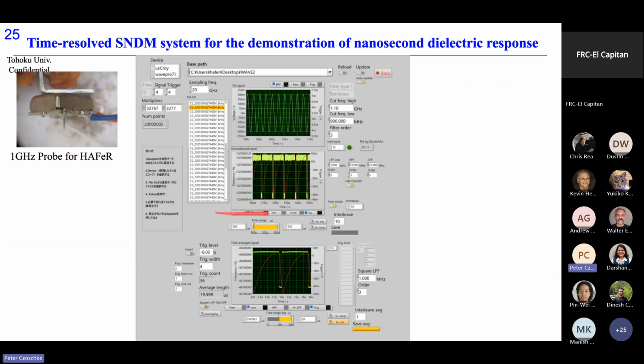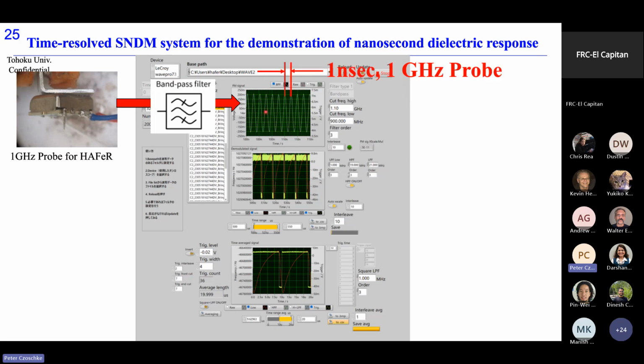And this is a shot of the PC display. We use the 1 gigahertz probe in this experiment, and at first, this microwave signal is directly acquired by the digital oscilloscope. Then this is the waveform of the detected microwave signal. You can see the period is 1 nanosecond. This means the signal is 1 gigahertz.